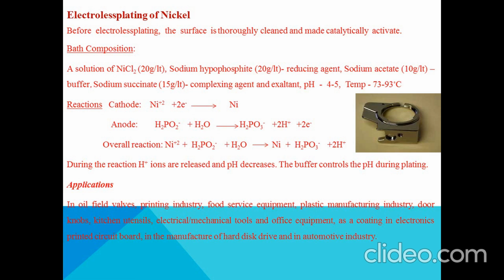Complexing agent will form a complex compound with the metal ion, thereby reducing its concentration in the solution in order to get a thin and good coating. The excitant will increase the rate of the reaction. pH of the bath is maintained between 4 to 5 and temperature between 73 to 93 degrees Celsius. During electroless plating of nickel, the reactions taking place are like this. The reducing agent sodium hypophosphite in the presence of water undergoes oxidation to form sodium phosphite, liberating electrons. So this is the anodic reaction and it takes place on the surface of the substrate.